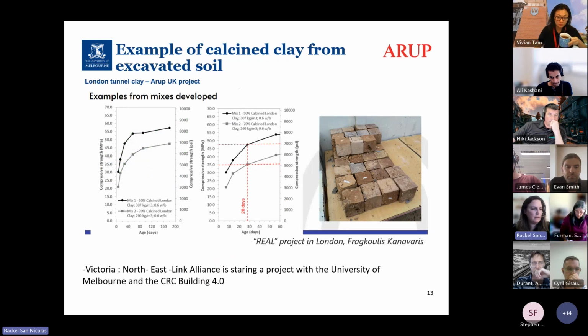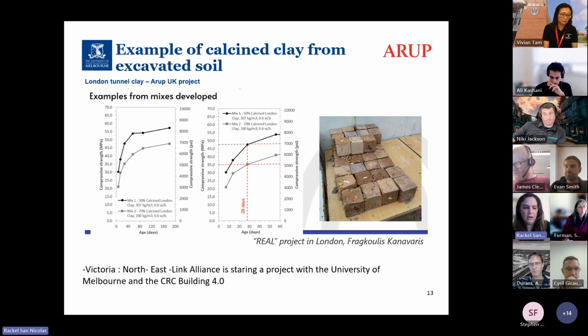I just wanted to mention this project to talk about how pure the clay needs to be, or where it needs to be from. This project was led by Arup. It's a real project in London, where they have been able to recycle excavated soil and London tunnel clay in order to make samples and test them in an LC3 kind of system. But there were two LC3 systems, one with 50% of the cement substituted and another one with 70% of the cement substituted by a combination of limestone and calcined clay.